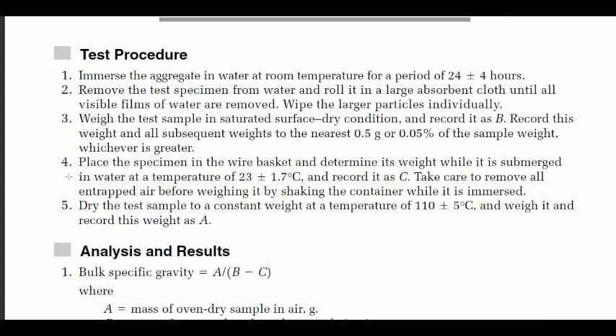We have like 5 steps. We need to stick to them in order to make this experiment. Firstly, we need to immerse the aggregate in water at room temperature for a period of 24 hours plus or minus 4 hours. So we take care, this is the period. Maybe in our experiment we're not going to do this exactly, but anyway, this is the standard one based on ASTM. The second step is remove the test specimen from water and roll it in a large absorbent cloth until all visible films of water are removed.